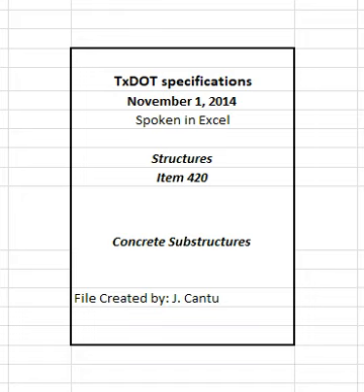A curing day is a calendar day when the temperature, taken in the shade away from artificial heat, is above 50 degrees Fahrenheit for at least 19 hours or, on colder days, if the temperature of all surfaces of the concrete is maintained above 40 degrees Fahrenheit for the entire 24 hours. The required curing period begins when all concrete has attained its initial set unless indicated otherwise. Tex-440-A may be used to determine when the concrete has attained its initial set.